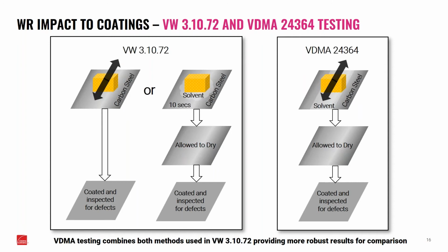So one of the ways that they test for this, they use the VW 3.10.72 that's been referenced in the marketplace. What they'll do is they'll take a sample of this insulation, they'll scrub it across the surface of carbon steel, and then they'll coat that piece of carbon steel, and then they'll look for defects.